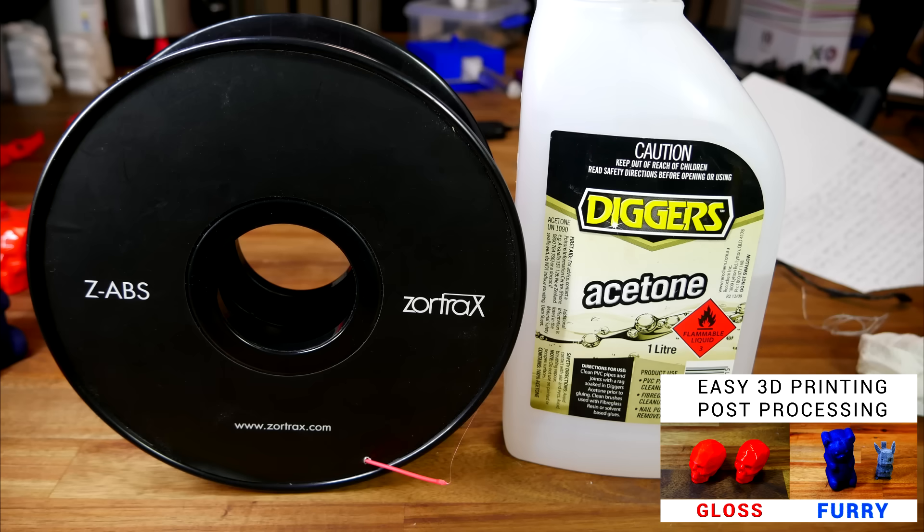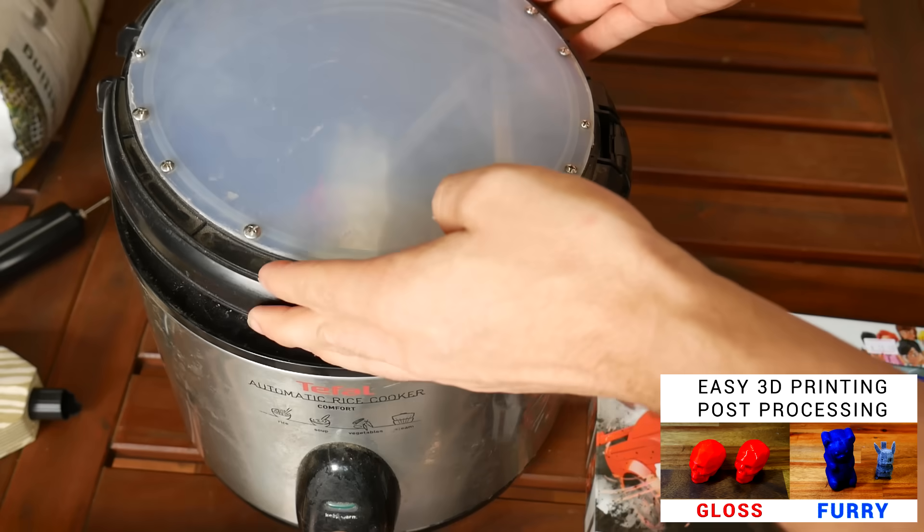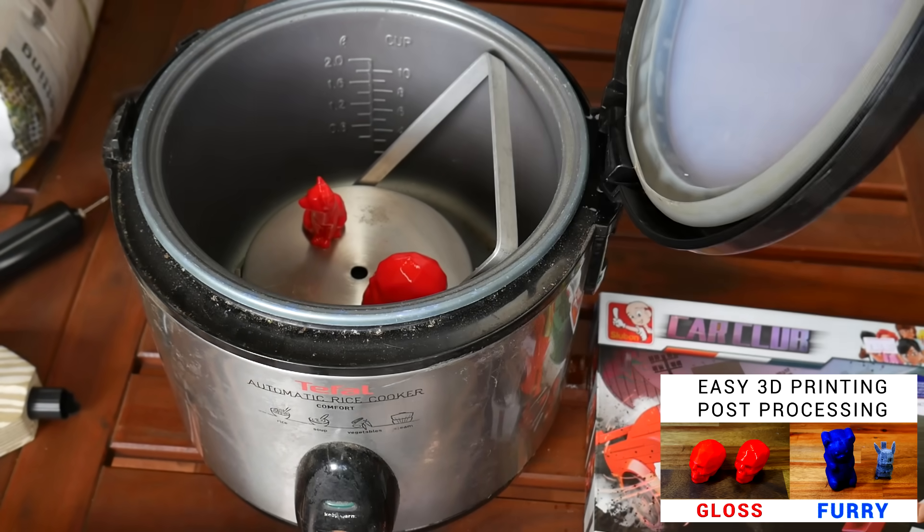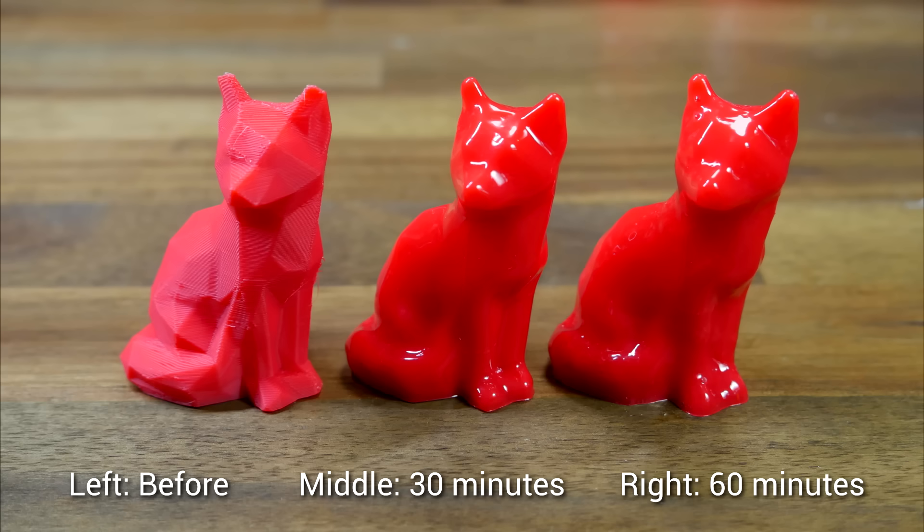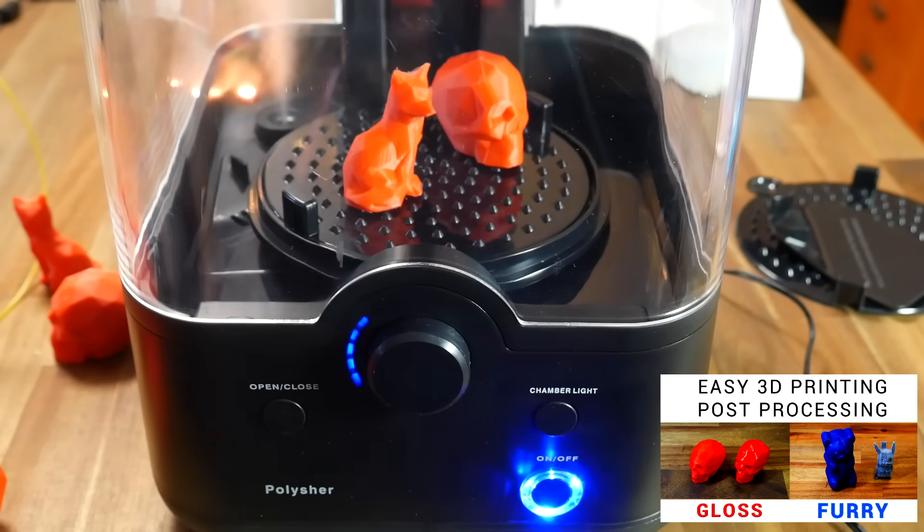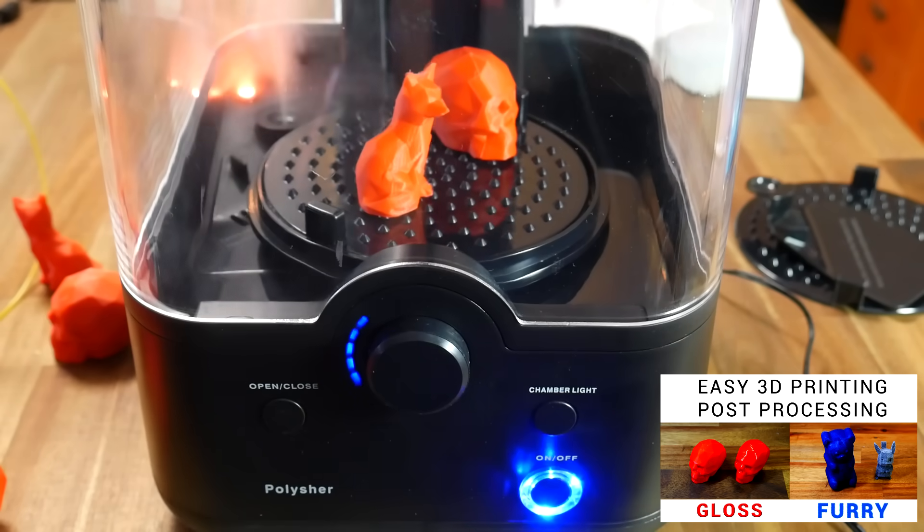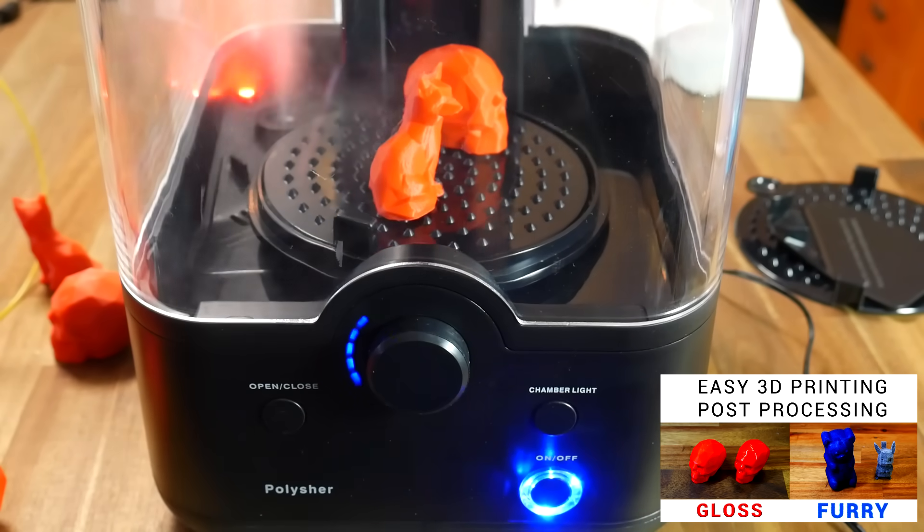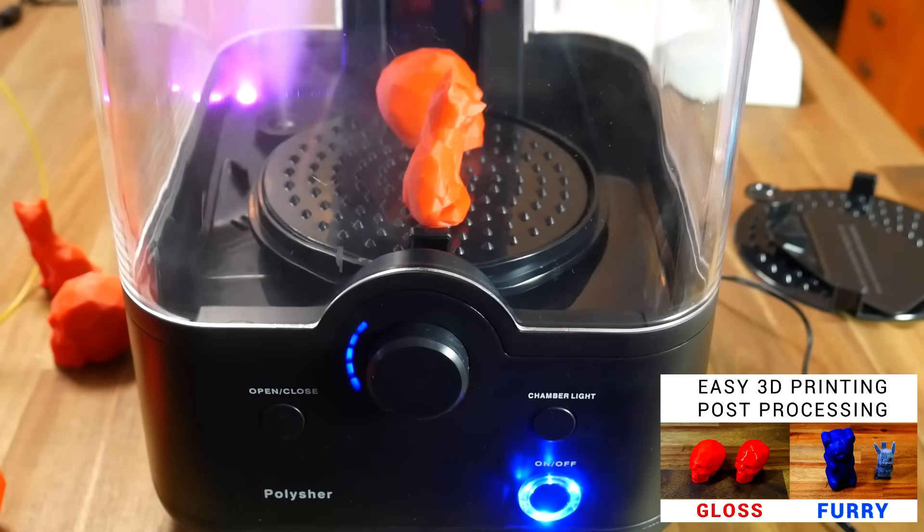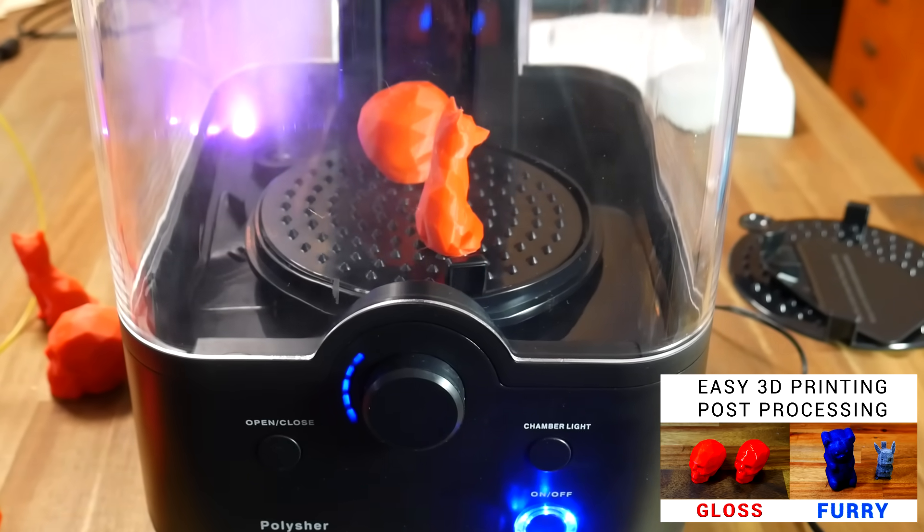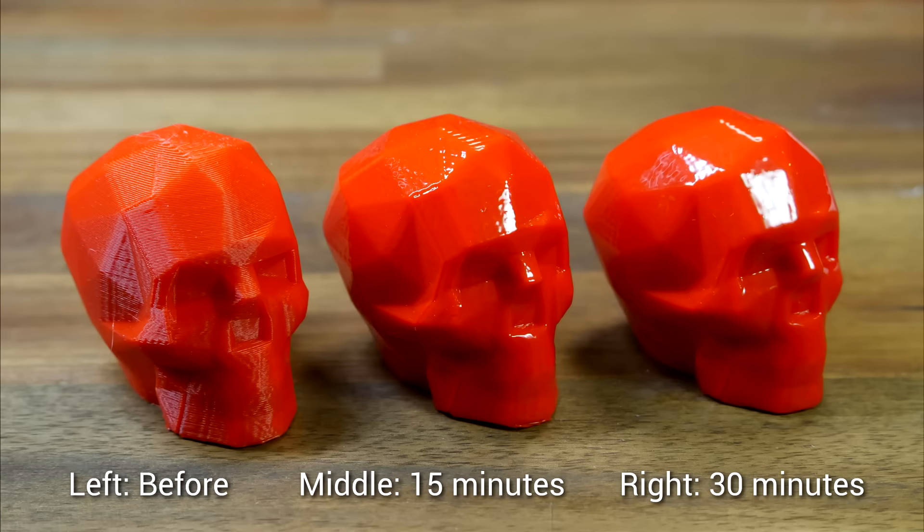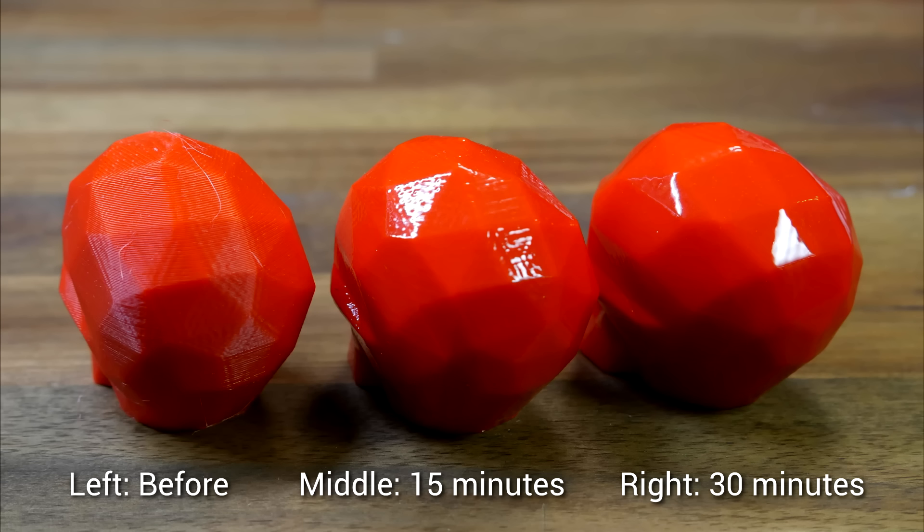In the past I've also covered techniques like using a solvent in vapor smoothing. For instance acetone with ABS or ASA and in my case I use a modified rice cooker with very consistent results. The only problem being the smoother you get it the more detail you'll lose. There's also proprietary versions of this like the Polysher from Polymaker that uses isopropyl alcohol with their own blend of PLA which gives pretty similar results to ABS with acetone. Of course this doesn't warp like ABS so it's a lot easier to print.